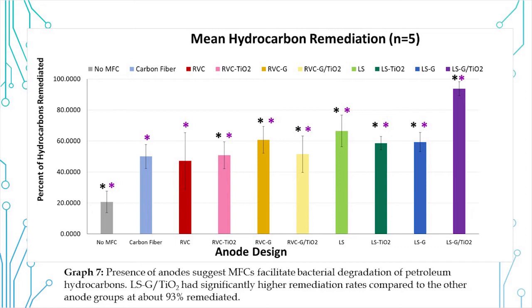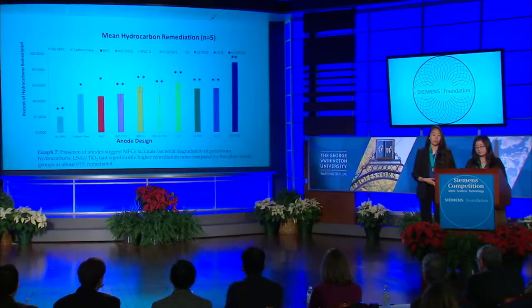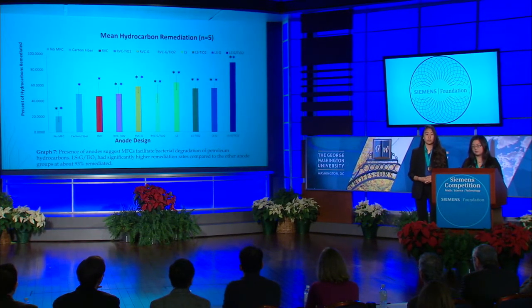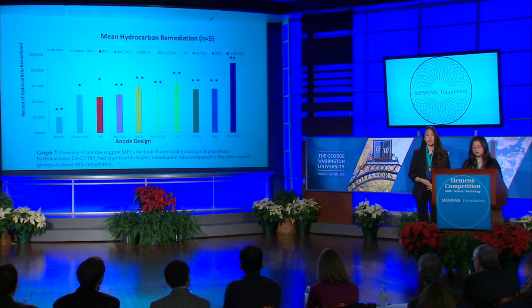For the mean hydrocarbon remediation graph, all groups containing MFCs had a significantly higher percentage of oil remediated when compared to the no MFC group. This supports Liu's study that MFCs can be implemented in an oil spill region. According to Morris, the MFC anode in its solid state can function as an alternative electron acceptor and facilitate the oxidation of the hydrocarbons. Interestingly, only the loofah sponge composite has a significant difference among the anode groups, with it degrading 93% of the oil. This indicates that for significantly enhanced degradation rates, optimal structure and surface coating is required.